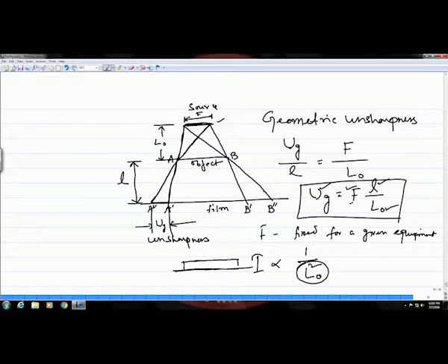Okay. So, that this distance L naught, sorry, this distance L is minimized. Okay. So, in this case, when you keep them in contact, L will be simply the thickness of the film, T f, plus the thickness of the sample or of the object, T s. Okay. So, since the film and the object are in contact, this is also known as contact radiography.